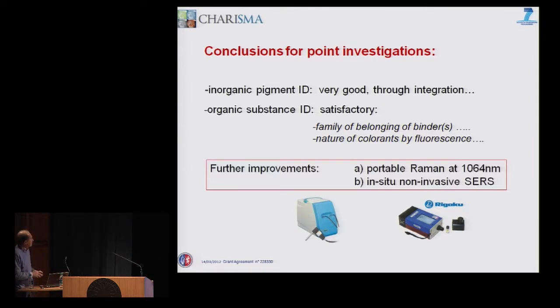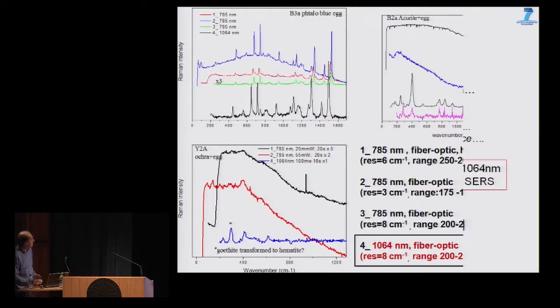The possibility to carry out measurements using portable Raman with excitation in the near infrared. If you use portable Raman with excitation at 1064 nanometers, you can eliminate the fluorescence and the matrix effect, and you can see colorants better, for example. Another possibility is to carry out in situ non-invasive surface-enhanced Raman spectroscopy. This is quite ambitious. There are some activities that are going on.